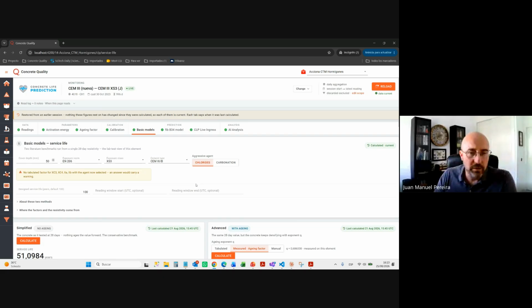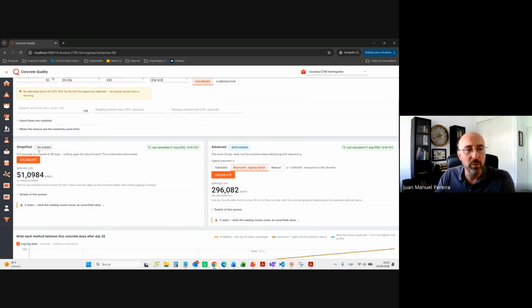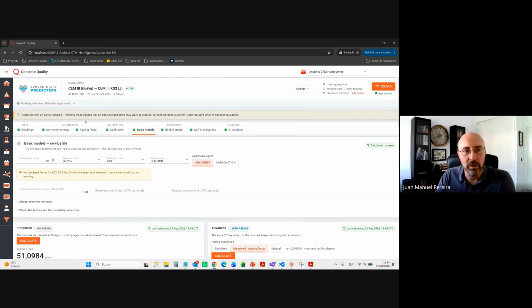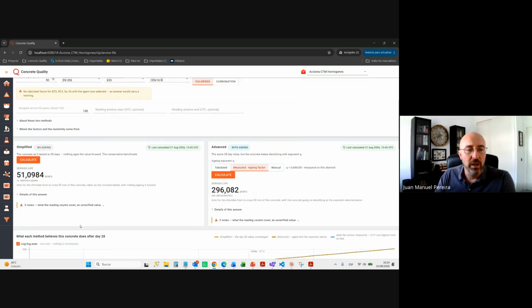So we have these two models. There is a very basic model, a simplified model with no aging, meaning that we don't count this aging factor. And this is based on the 28 days result. So if the concrete stopped at this moment and you expose it like that, how many years will it last? That marks the bare minimum of the service life. So in this case, it's 50 years. This is a 100-year concrete. So the bare minimum at 28 days is 50 years in this case. So this is a very good concrete.